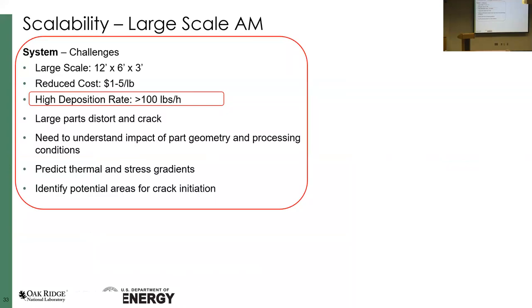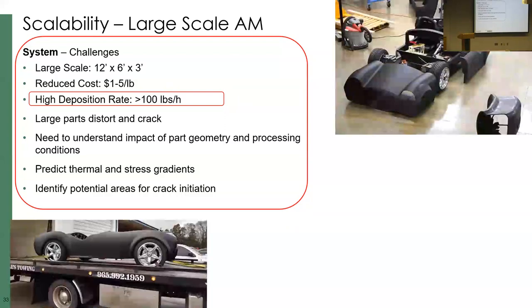We go up to 100 pounds per hour, increasing the throughput more. So instead of this small screw that is going around, I don't know where, don't take it, it's government property. By the way, if you take it, you are in deep, deep trouble. That's it, right? But we moved from this up to an extruder that is almost half of my size, a really, really large screw, 100 pounds per hour.